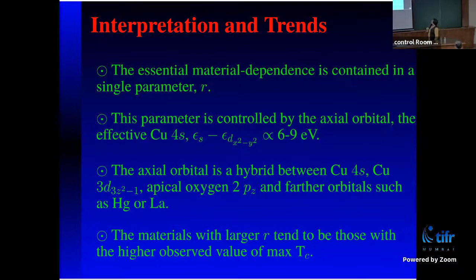So the essential material dependence is contained in a single parameter R. That was the point of our whole exercise. And this parameter is controlled by the axial orbital, which is actually a hybrid between copper 4s, apical oxygen PZ, and also maybe copper 3z square, and also maybe lanthanum or mercury, but all has to couple in this direction. Do you not see any contraction on the equatorial oxygen? No, there is nothing. So everything is happening in this direction.